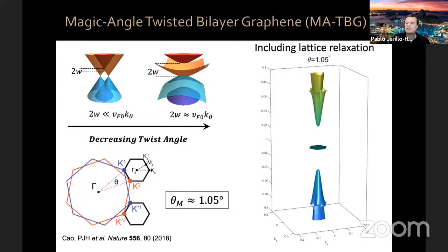Very good question. There are many ways of determining the twist angle. From electronic transport, you can look at what happens in a magnetic field. In a magnetic field, you have Landau fan diagrams, you have Landau levels, which tell you the density of your system, okay? And you can identify from those Landau fan diagrams the exact density at which you have 2 or 4 electrons per Moiré unit cell, okay? Once you know the density and you know it corresponds to 4 or 2 electrons per Moiré unit cell, you know the size of your Moiré unit cell, which directly gives you the twist angle, okay? So that's how we do it from the electronic transport point of view.